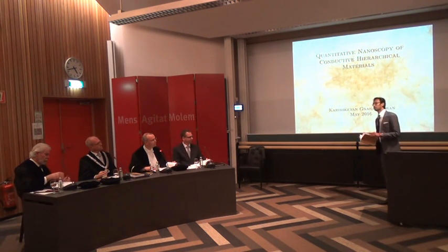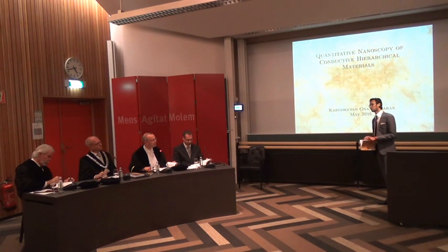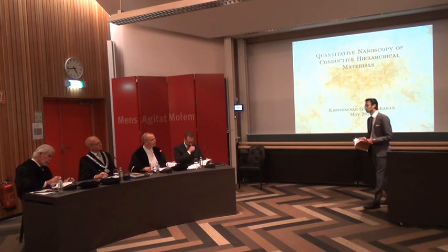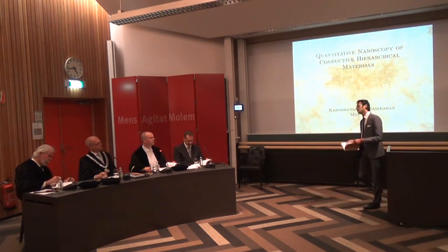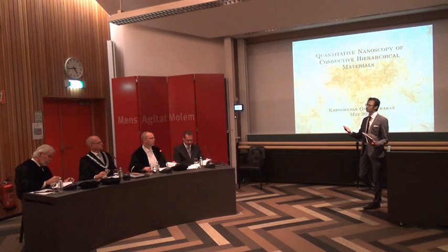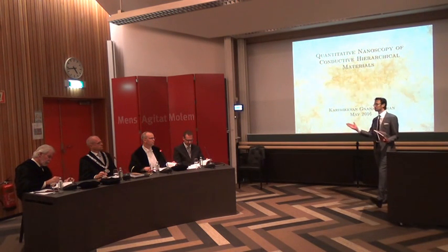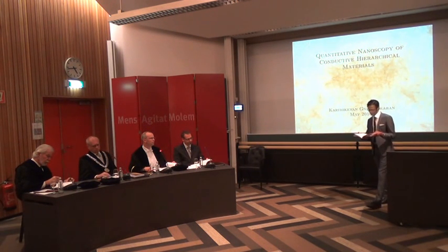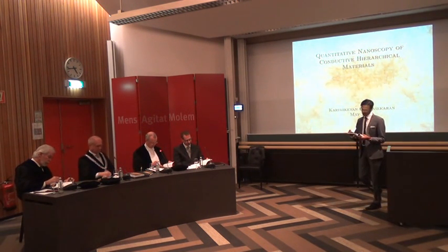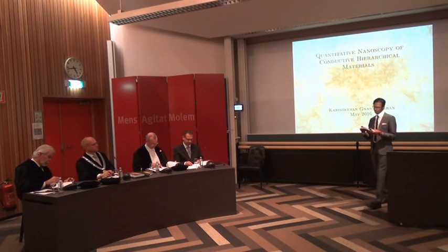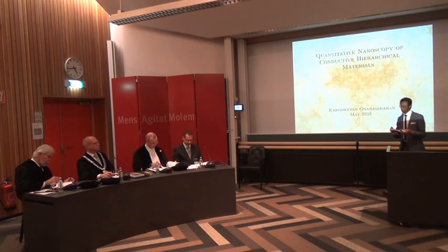The problem with experiment is you don't know the exact thickness. You do microtoming, you believe that it is 100 nanometer, but actually it would be 150 nanometer or even sometimes 200 nanometer. But in simulation, you fix the thickness exactly 100, 200, whatever you want. So I believe this is mainly due to the section thickness variation in the experiment, which shifts the curve a little bit. So if you see page 47, where the simulation and experiment at certain specific camera length, it shifts.